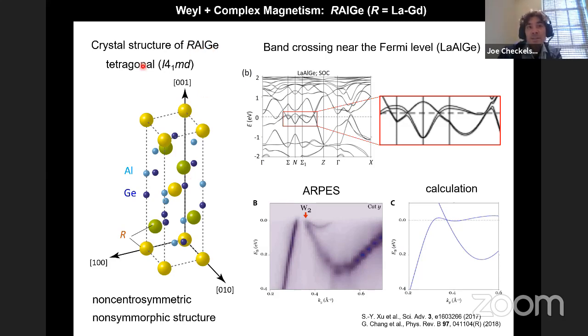What they are is, even with a non-magnetic rare earth on this site, these are expected and were shown to be Weyl semimetals. And the point is that they have a screw axis. I don't know if you remember 50 minutes ago, at the end of the animation I was showing you, the atoms were moving in this screw type fashion. There's a so-called 4-1 screw axis which runs through this crystal. And what it gives you, from a prediction and then from these photoemission experiments, are these Weyl type crossings. And they're unusual crossings, this so-called type 2 crossing. There's also type 1 crossings.